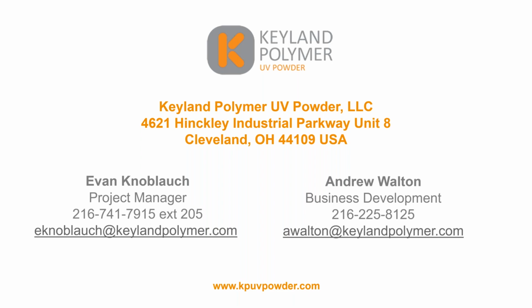But it wouldn't be possible to do both the metal and the plastic in one go, probably. It depends. There are some applications where we've used the same powder on a polycarbonate ABS blend and on an aluminum component, and they both worked well. The same powder had very good performance on both of those substrates. So it does vary depending upon the mix of materials. The tweaks in the powder might be small, they might be large, just depending upon the mix of material that we're working with.